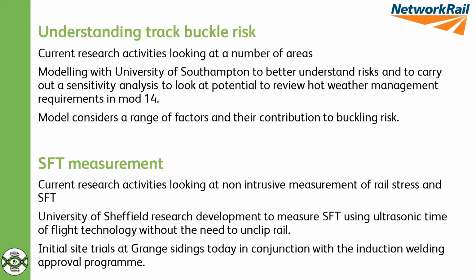Generally, it's okay, provided we have identified any deficiency or disturbance or loss of SFT or low SFT, but understanding which of those becomes more critical. And certainly the SFT itself is something key. And actually, we're doing this testing today as we speak now. They're out doing some measurements with new technology using some very clever time of flight technology with ultrasonics to look at potentially being able to measure the SFT from a rail condition without the need to perhaps unclip the rail or to cut the rail, to go into a site blind effectively and record it.